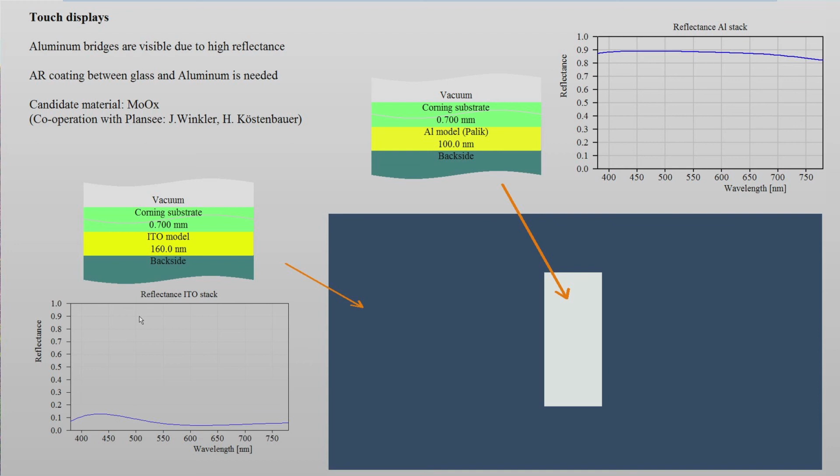This is a problem from display technology. My customers produced ITO layers on Corning substrates, and there's a backside material which is not too relevant for this discussion here. And the main area of the display is just covered by this layer stack: Corning substrate, ITO layer, roughly 160 nanometers thick, and the backside material. But in addition to this main viewing area of the display, there are little contact sections where they need a high conductivity, and the ITO is not conductive enough. So in these bridges, they use aluminum instead of ITO,